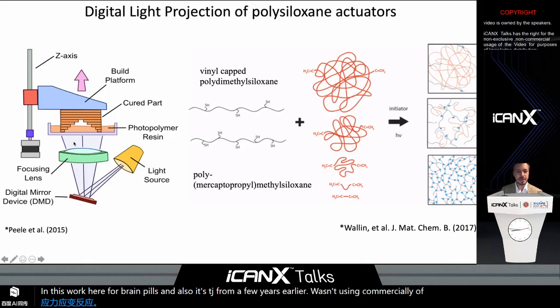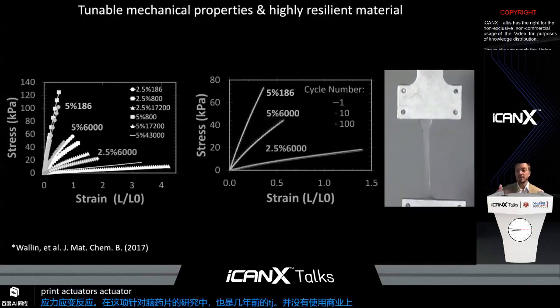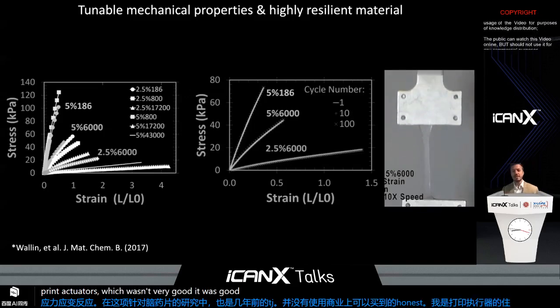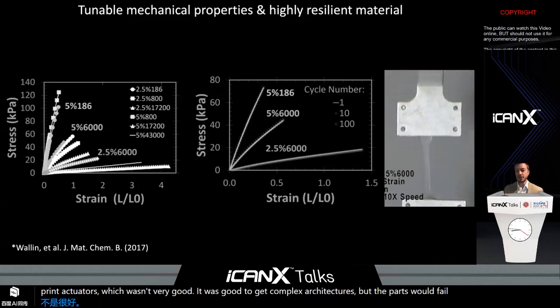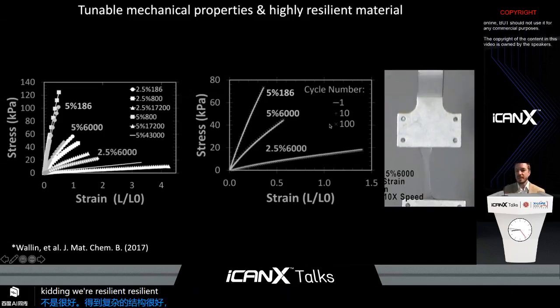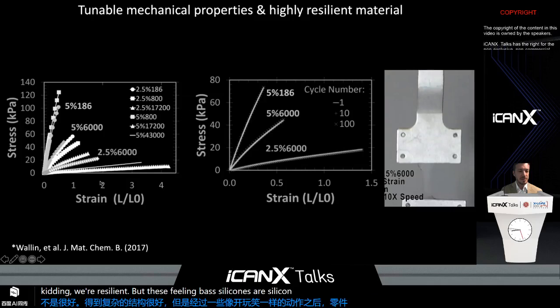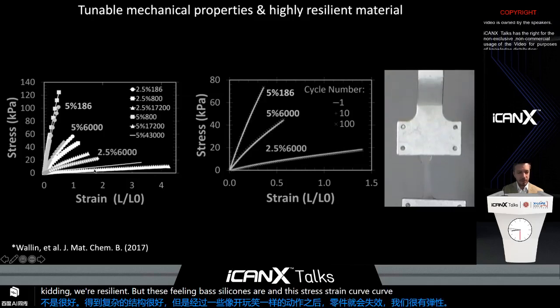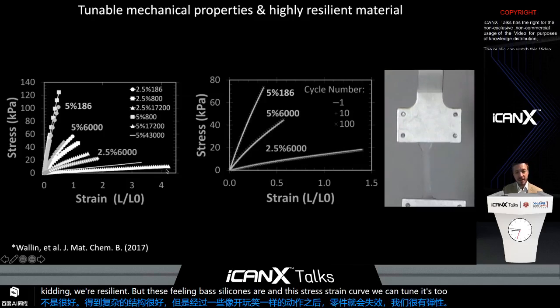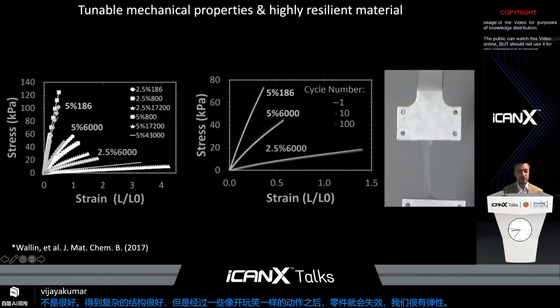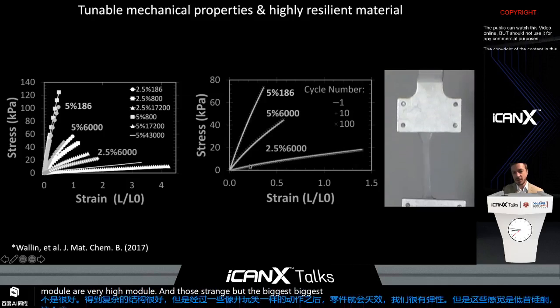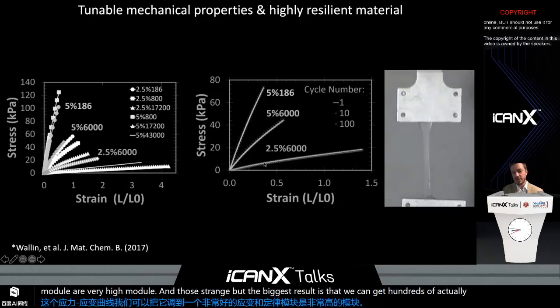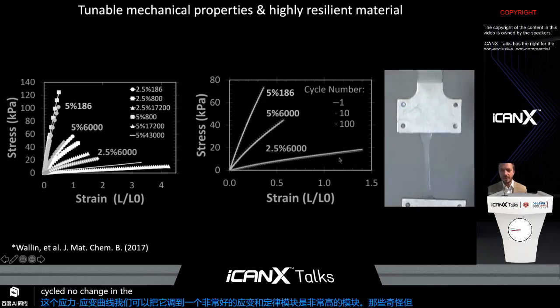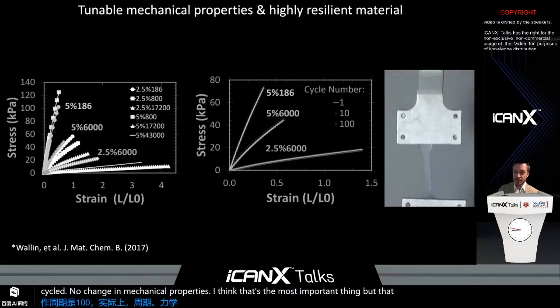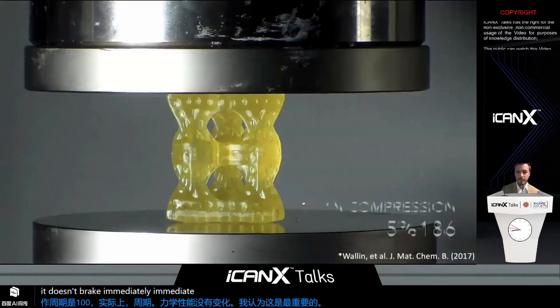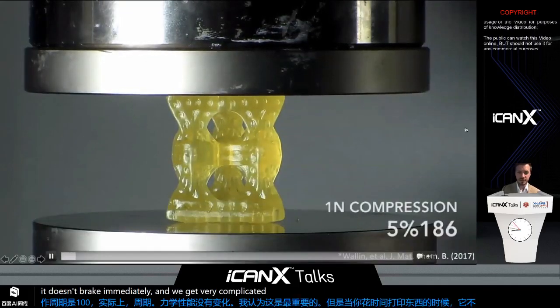And this work here from Brian Peel and also TJ from a few years earlier was on using commercially available elastomer resin to print actuators, which wasn't very good. It was good to get complex architectures, but the parts would fail after only a few actuation cycles because they weren't resilient. But these thiolene-based silicones are, and with this stress strain curve, we can tune it to be very high strain and low modulus, or very high modulus and low strain. But the biggest result is that we can get hundreds of actuation cycles, or 100 actuation cycles, with no change in mechanical properties. And I think that's the most important thing, that when you spend the time to print something, it doesn't break immediately.